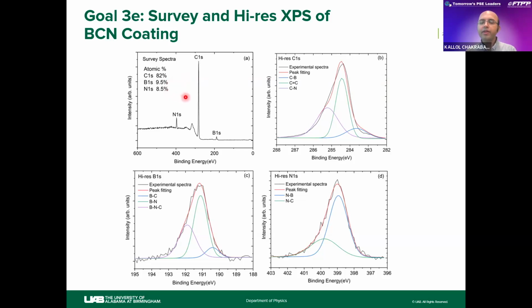The stoichiometry of BC10N requires more carbon and a 1-to-1 ratio of boron and nitrogen. According to our survey spectra, the boron to nitrogen ratio is almost 1, and the carbon to boron and carbon to nitrogen ratios are about 10-to-1, so it closely matches the stoichiometry of BC10N.